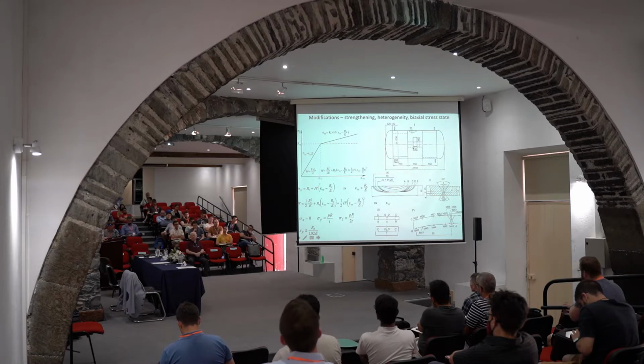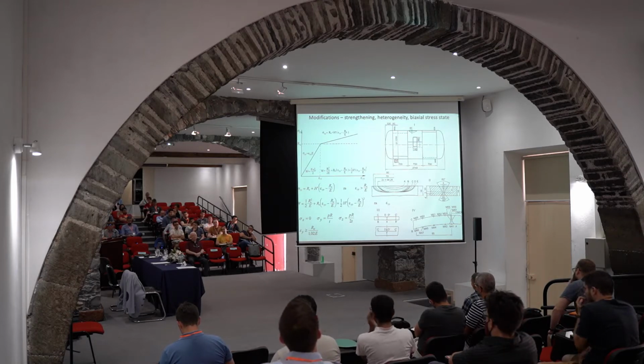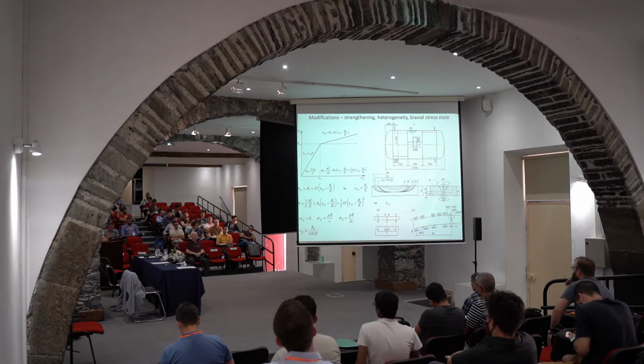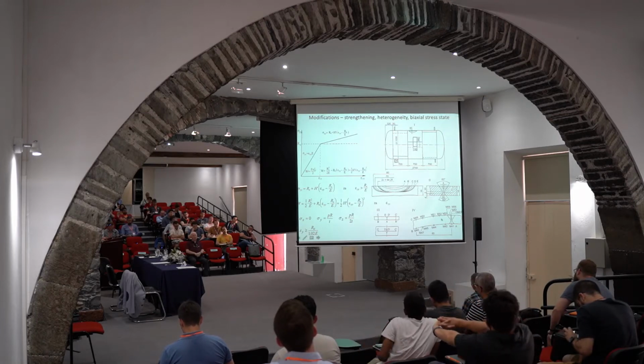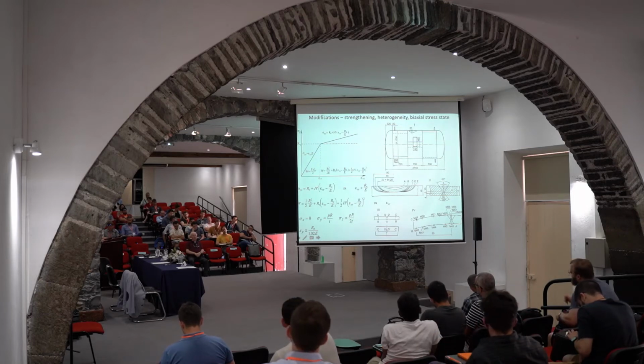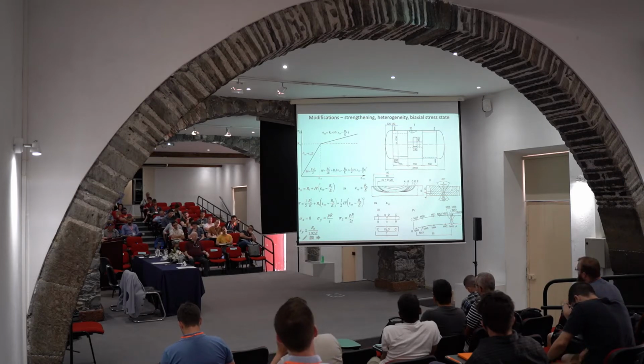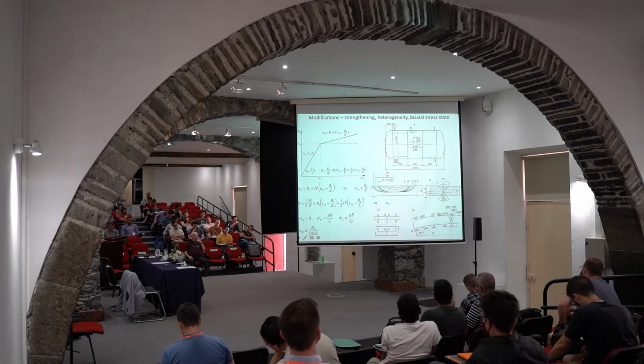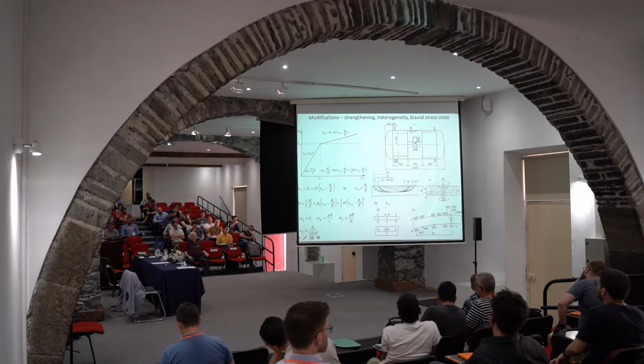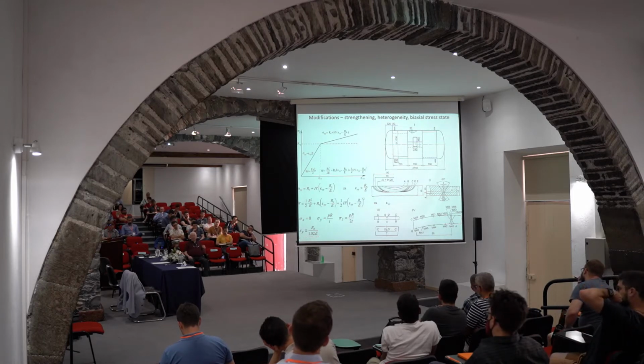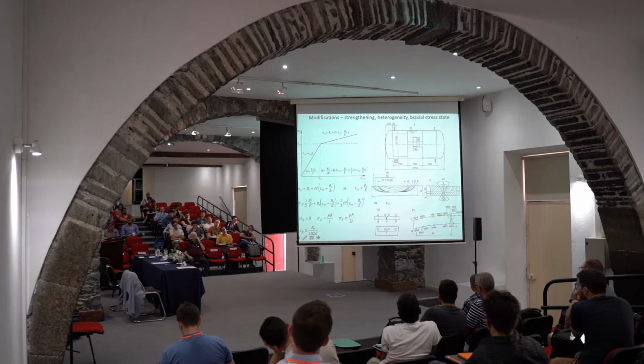I forgot to mention, while we had it in our hands, we instrumented it with strain gauges. And then there was a special design how to do that, so that those strain gauges inside the pressure vessel really work. It's not simple, but we were successful in doing so. And you can see here at the bottom, M is representing strain gauge, and of course crack mouth displacement was another parameter that we needed. So this is valid only for the outer cracks. For the inner cracks we can't do it. And here is the path of measurement.